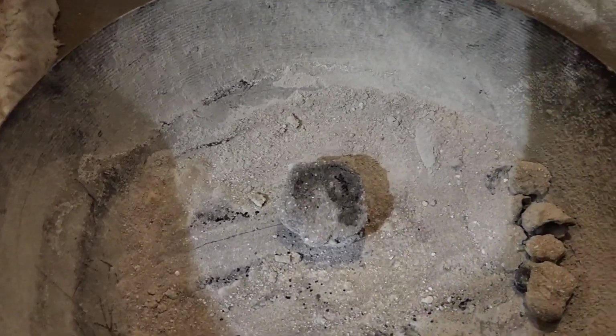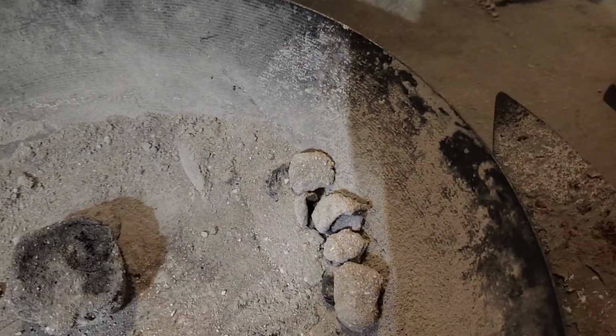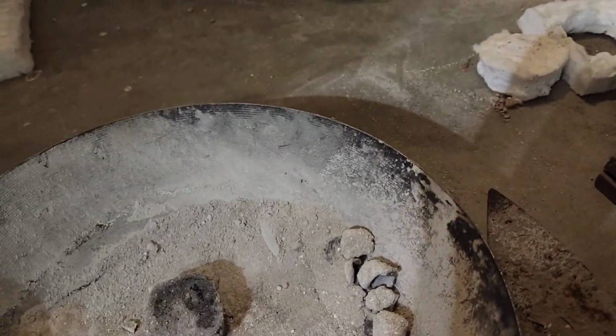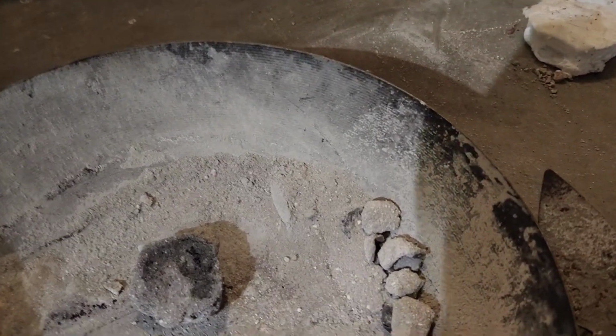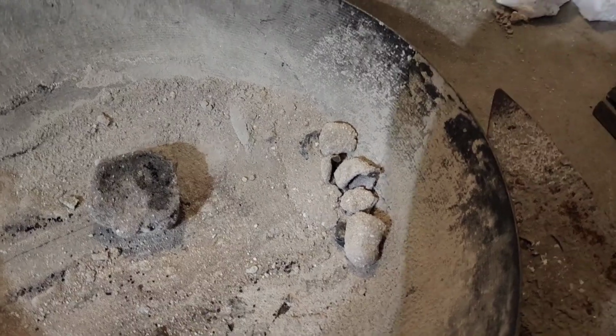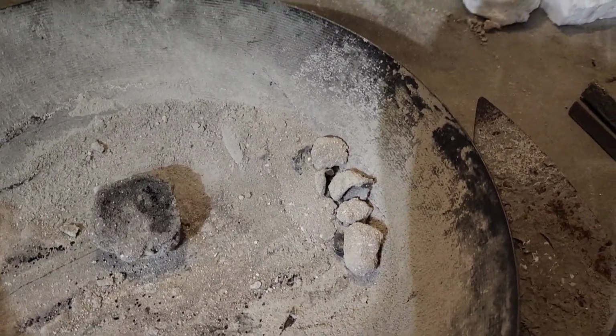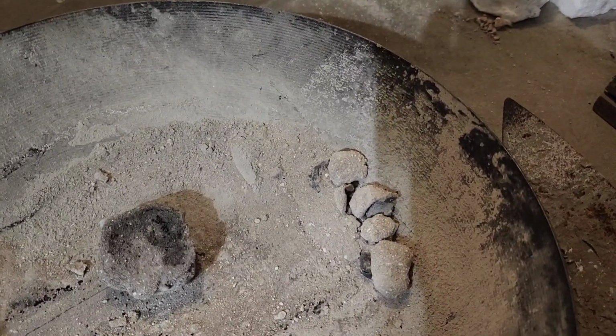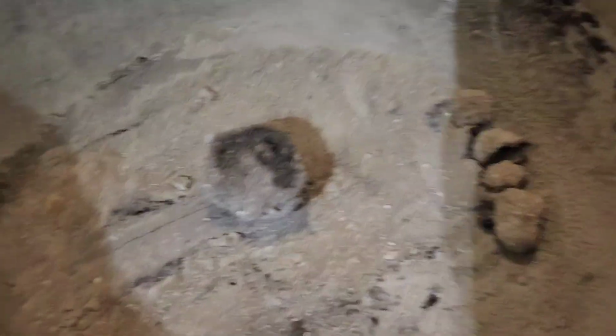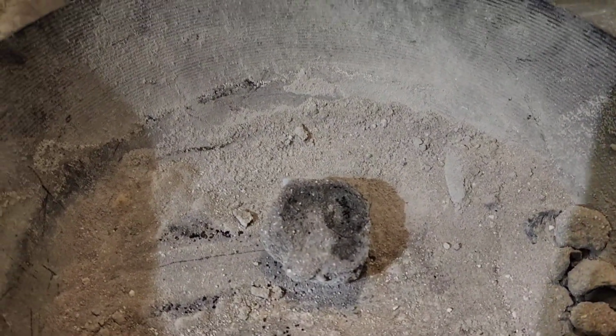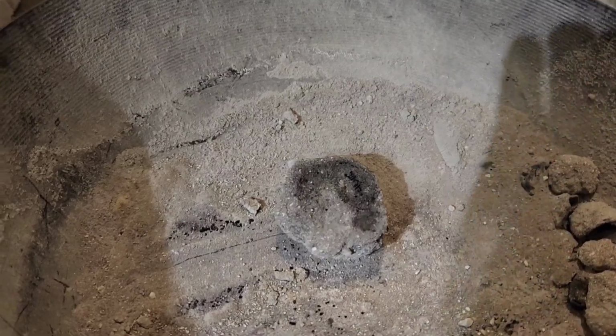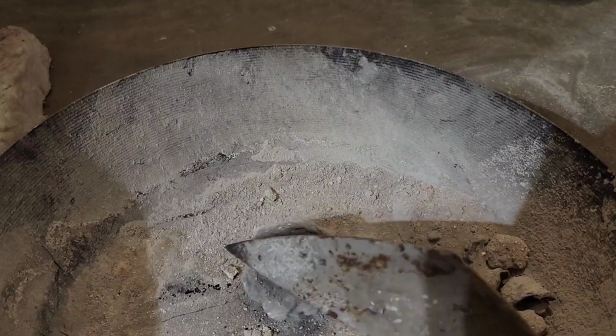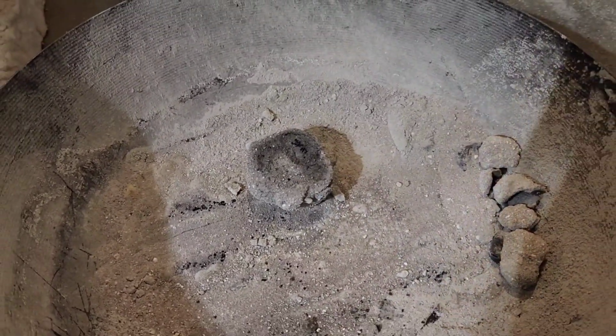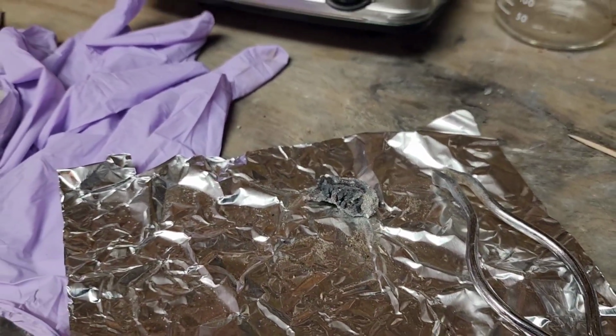Alright, so the first singular microwave arc sinter phase, let me take this mask off, was not successful, but it still had a few bits of beading around the surface. This is the microwave arc sinter plus the pre-sinter. Pretty hard casing. We're going to excavate this and see what we have. Alright, well, not a total failure.